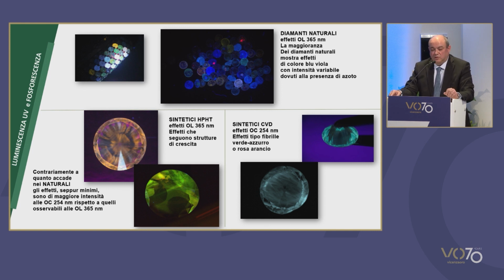CVD synthetic diamonds can have this greenish or blue color, which is different from the blue that you see above, with some fibrils inside, which reflect the deposition of carbon atoms which has occurred during this process. Now, if you look at them with short wave or long wave, you can also see some figures, butterflies or crosses, and this could be a bad sign. So you should have some doubts about these stones.